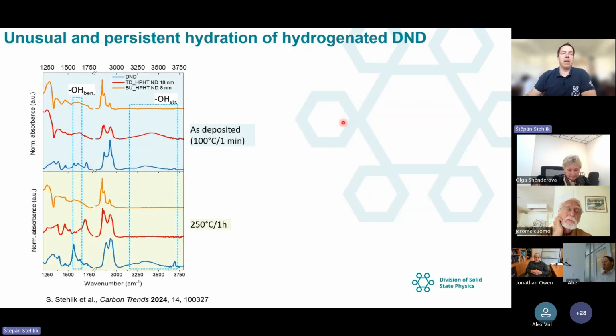Okay, and the other parameter which we found is different is the hydration. So you can see again on the FTIR spectra of the freshly deposited samples that we see quite common OH signal on the DNDs. We saw something also on the HPHT top-down in this case, but we saw nothing on the bottom-up HPHT nanodiamond. So the affinity to water here was the lowest. And it was also confirmed when we annealed the sample, we still saw the OH and the water on the DNDs, but not on these HPHT types.